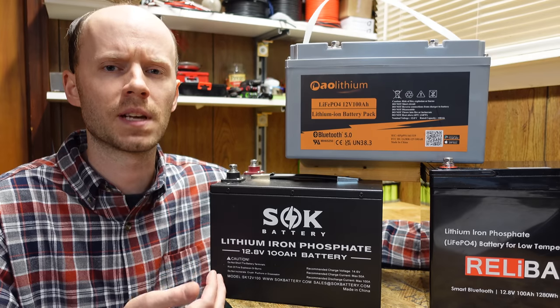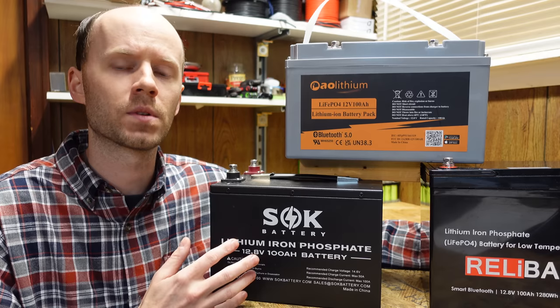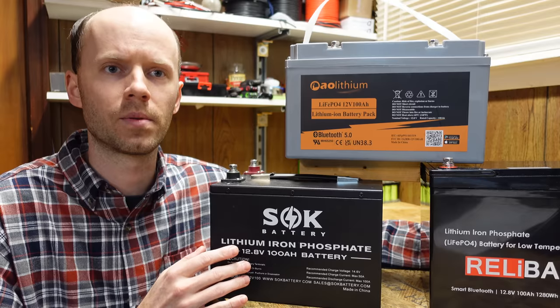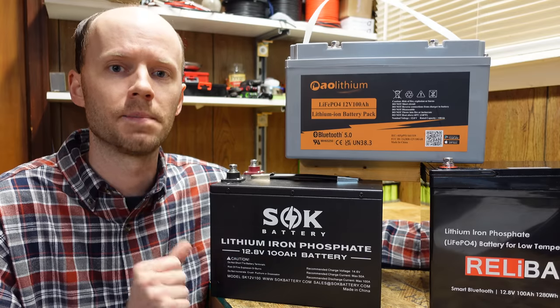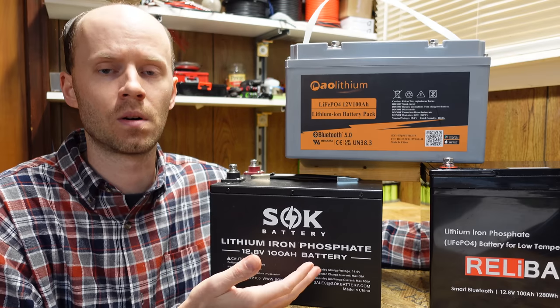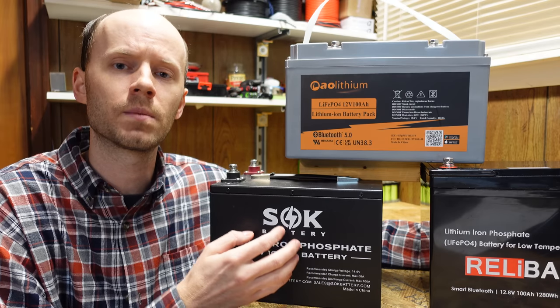Additionally, the alternator and the regulating circuits in cars are designed to charge lead acid batteries, not lithium iron phosphate batteries. Typically, your alternator is going to be around 14.7 volts — it could reach as high as 15 volts. If you divide that out by four cells, that's actually above 3.65 volts per cell. 14.7 volts is around 3.67 volts per cell. So you run the risk of the BMS shutting the battery down from overvoltage of the battery as a whole, or overvoltage of any specific cell, even if your cells are 100% perfectly balanced.